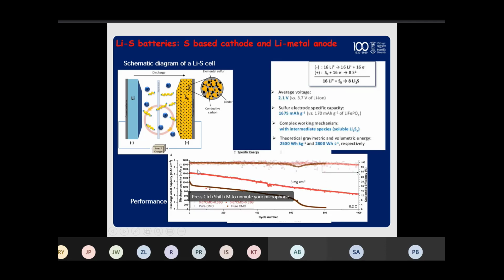Just to give you an idea, this is our own data of a lithium-sulfur cathode, from our collaboration with Monash University, and you can clearly see the level of capacity that we can achieve with lithium-sulfur batteries, and also the cycle life. However, when we transfer the technology from coin cell level to pouch cell level, with much larger area electrodes, things are not as straightforward as they look. We are now trying to make sure that the same performance that we see at coin cell level, with 1 centimeter square electrodes, can be transferred to 20 centimeters square.